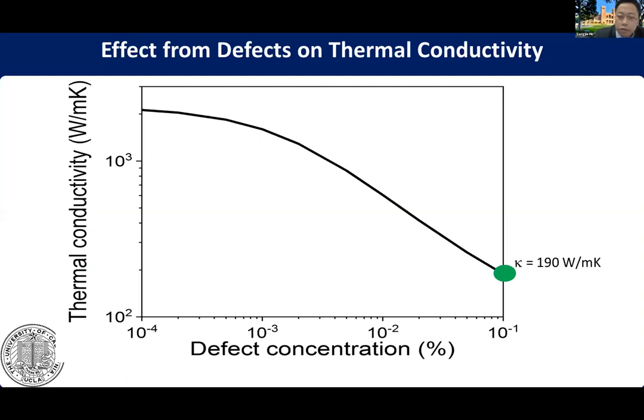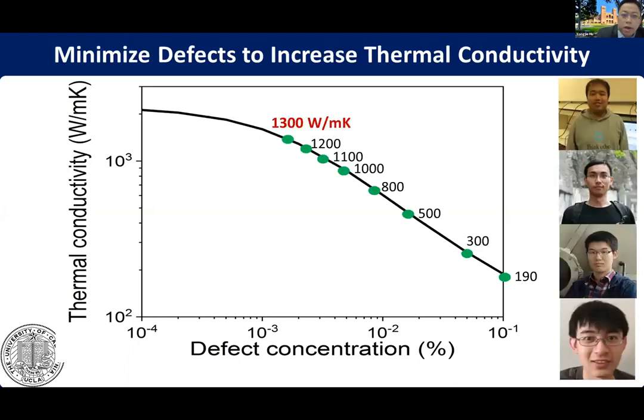Fortunately, we soon understood that there is strong effect from the defects on thermal conductivity that enhance the phonon scattering to reduce the thermal conductivity. Even 0.1% of vacancy defects verified by XPS can strongly reduce the thermal conductivity by over an order. So the key challenge is to minimize defects to increase thermal conductivity.